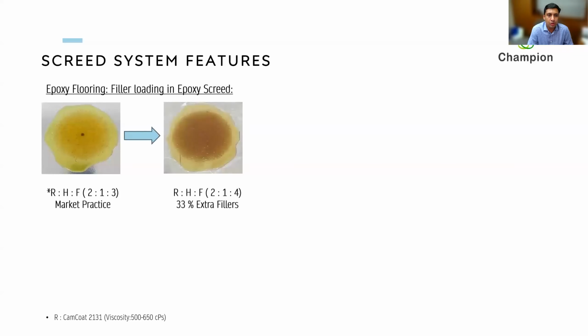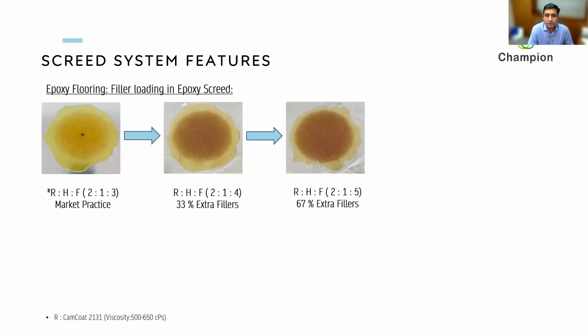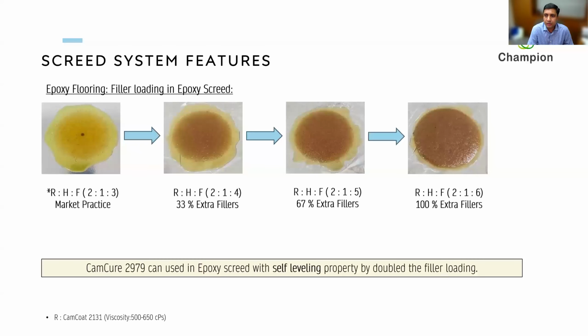In the second image, you will notice that we have added 33% more filler, and the system still remains a self-level system. In the third image, we have added 67% filler, and it continues to be a self-level system. And in the fourth image, we've added double the filler that was there in the first image, but it still remains a self-level system. So this is a very good system which can have a very wide range of filler dosage and still give you a self-level screed.